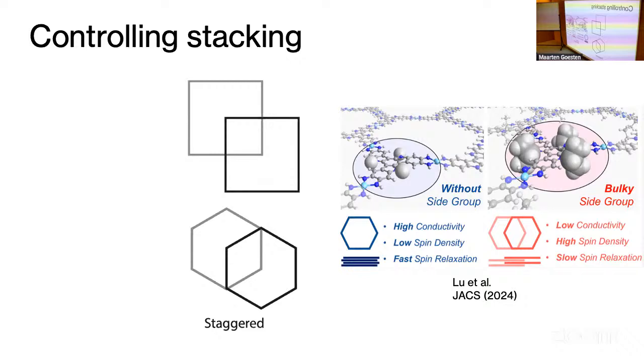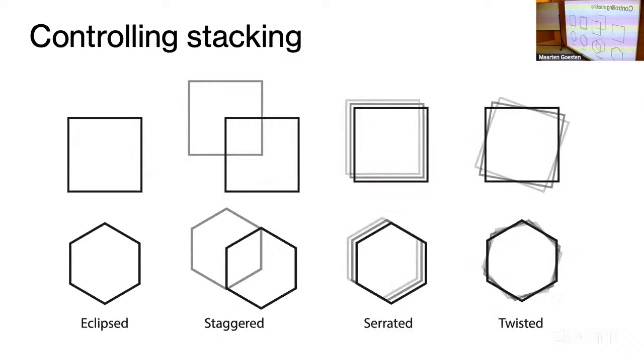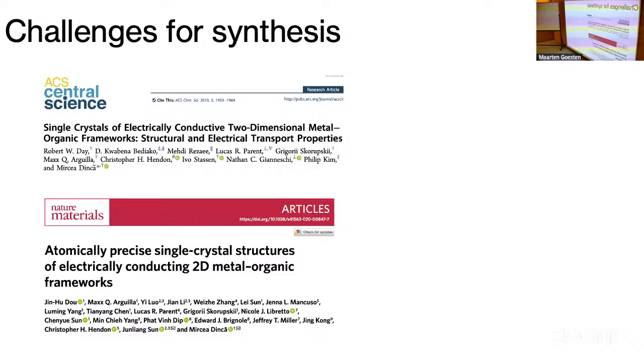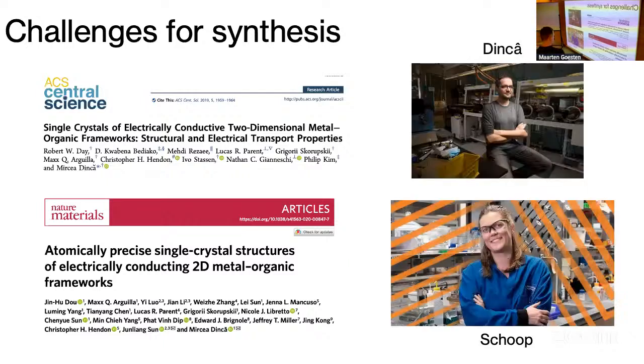There are also groups that are showing that you can use some polar alcohols, like just benzyl alcohol, to enforce some twistronics. So you can actually twist these or similar structures. Yeah, so this is what we have been working on a lot. These are my two collaborators at Princeton, experimentalists mainly, and a lot is going on here. So MOFs are usually very difficult to make single crystals of. There's been a lot of work done, so that's now becoming possible. But again, I emphasize, it does not mean that for all these MOFs we can control stacking.